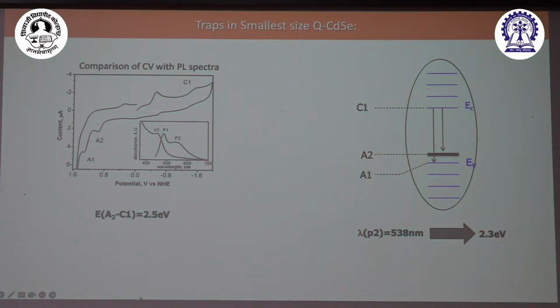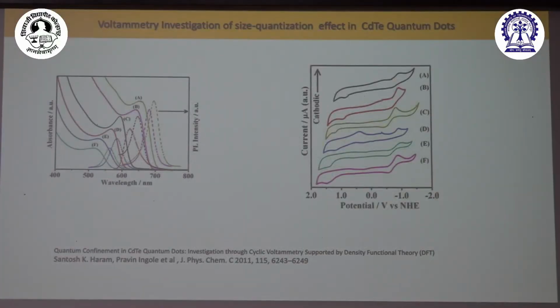The interesting part here: the smallest particle has got an extra peak here, A2. I had A1, I had C1, but I have A2 here. In luminescence, I got again one shoulder here, in photoluminescence. If I calculate the energy of that particular peak, it turns out to be 2.3 electron volt. If I calculate this energy for this peak, it comes to 2.5 electron volt. So these two numbers are very close to each other, which tells us that there are some states present within this band gap, because of which I got a shoulder in the luminescence, and also that gave me a peak somewhere here in the cyclic voltammogram. So there's a fantastic match between spectroscopy results and electrochemical voltammetric results.